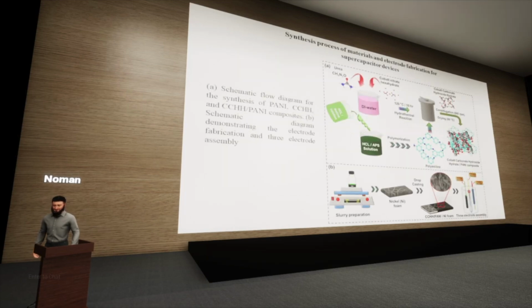This is the synthesis process of the materials and electrode fabrication for the supercapacitor device. This is the schematic representation of how we mixed urea and cobalt nitrate hexahydrate as precursors, and then carried out a solvothermal treatment followed by centrifugation and drying to form the nanocomposite. Meanwhile, we also added the polyaniline in the autoclave so that the polyaniline and cobalt carbonate hydroxide hydrate particles can join together to form the nanocomposite.